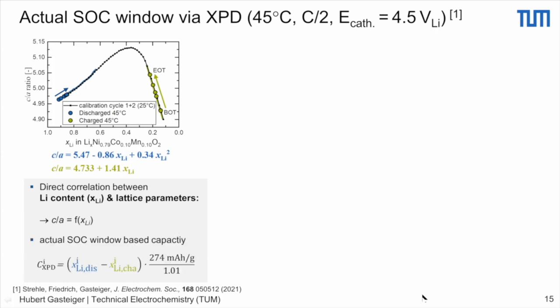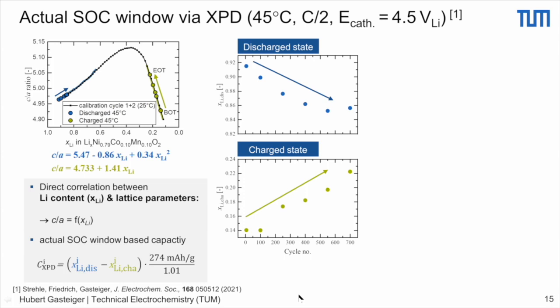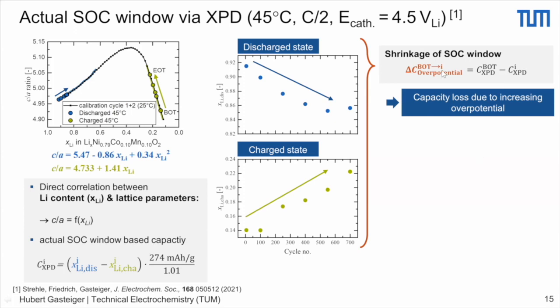And from that, we can calculate the capacity which would be due to simply cycling between these two windows, between the discharge state and the charge state. And so this delta lithium content multiplied with the total theoretical amount of 274 milliamp hours per gram, and then 1.01 accounts for this 1% lithium excess, we can calculate the capacity which we would expect based on these XRD measurements, right? And so what we record is the lithium content in the discharge state and in the charge state. And here we can get the shrinkage of the SOC window, which we can describe as a loss of capacity due to overpotentials, which is essentially the capacity which we get at the beginning of test minus that at the end of test, calculated by this equation here.